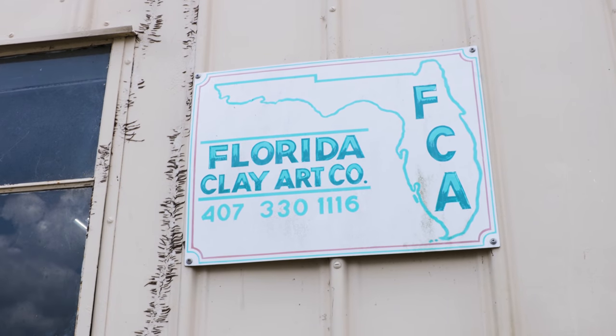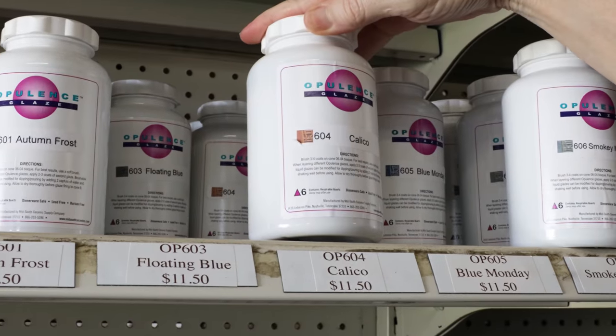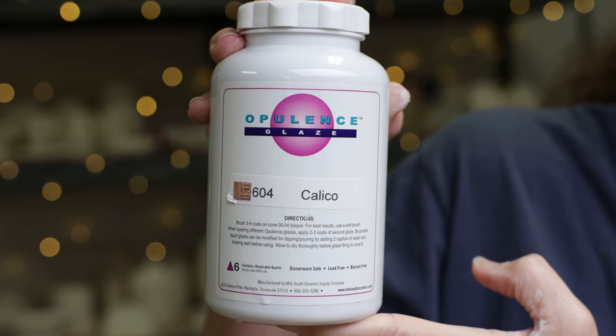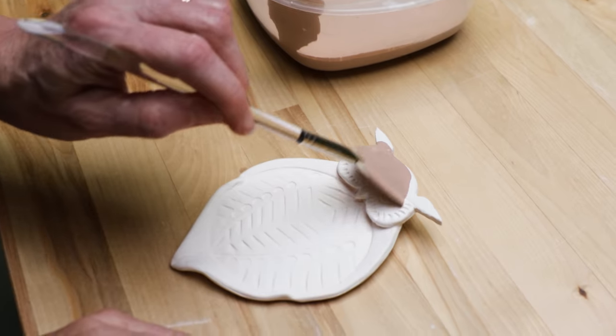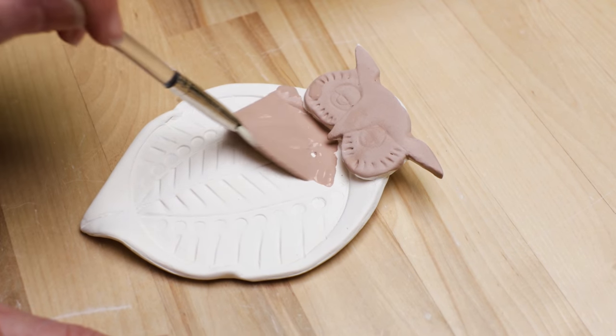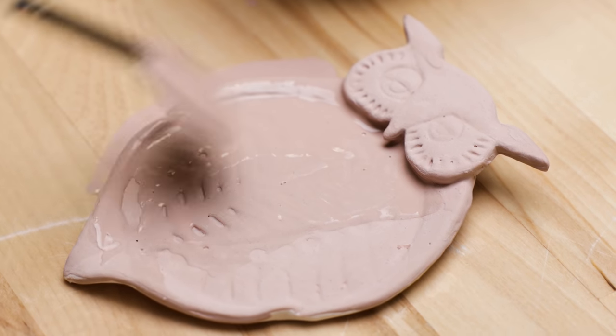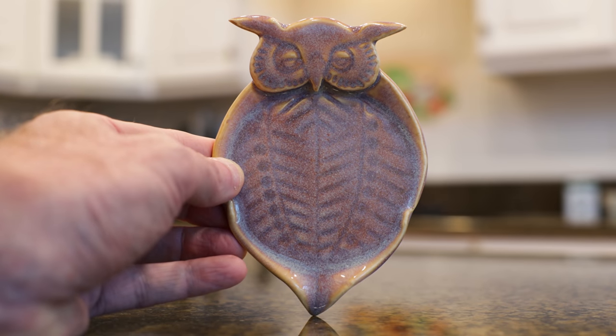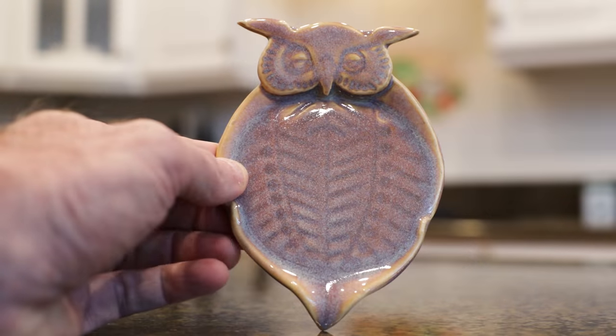When I was trying to figure out what glaze to use on the owl, Jim and I had to make a trip to Orlando to Florida Clay Art to pick up a new load of clay, and I thought we would pick out a new glaze to experiment with. We saw this Opulence 604 Calico glaze and thought we'd give it a try — the glaze always looked so nice on the sample tiles, but would it work on my porcelain? After shaking and stirring thoroughly, the glaze did appear a bit on the runny side. I brushed four coats on the surface per the instructions and made sure to work it really well into the texture. The glaze dried really fast upon application. I fired it to cone 6, and where the glaze was thinner on the highlighted areas it was a brownish color, and where the glaze was thicker it was purple and blue. It compared really well with the sample tile.